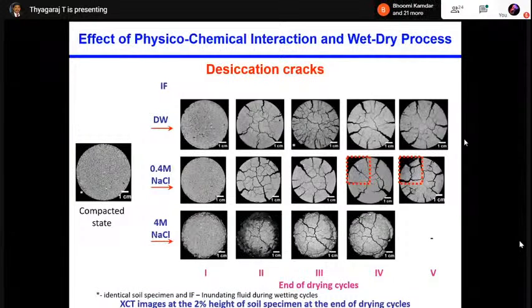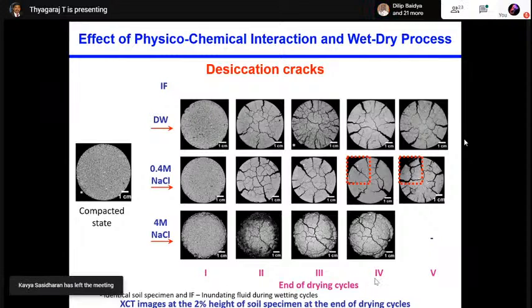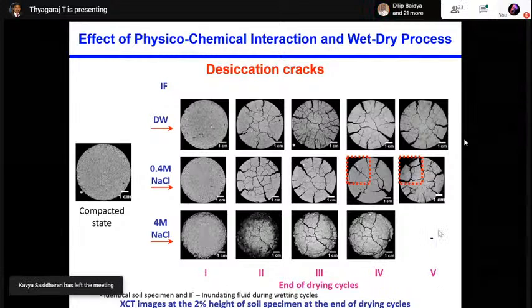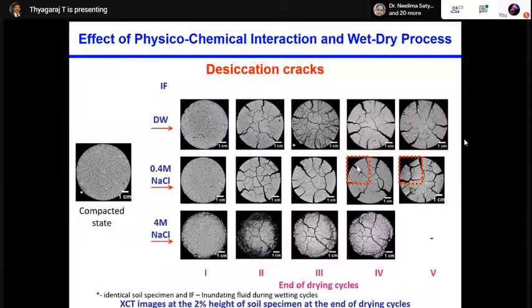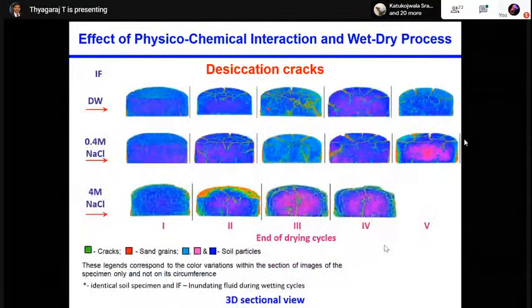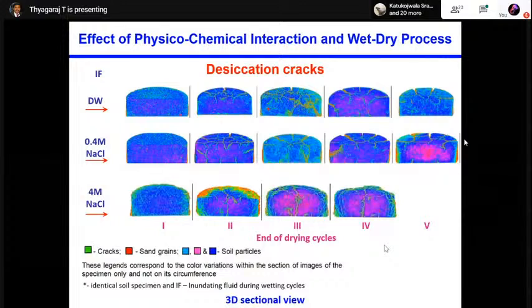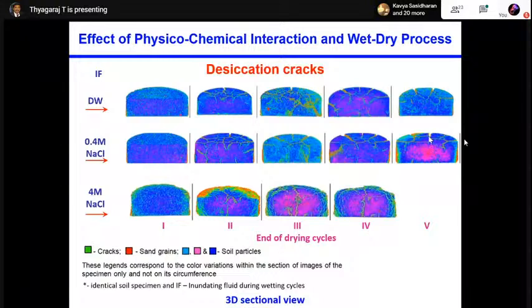So we can see that with the 4th drying cycle and the 5th drying cycle with 0.4 molar NaCl solution, you can see the cracks are occurring at the same place. Whereas in case of 4 molar NaCl solution, it starts to happen from the 3rd cycle itself. Right. And we have reconstructed these images using the XCT software. You can see the crack pattern, the crack is occurring at the same place in case of 4 molar NaCl solution. But whereas in case of the distilled water specimen, it was not occurring at the same place.